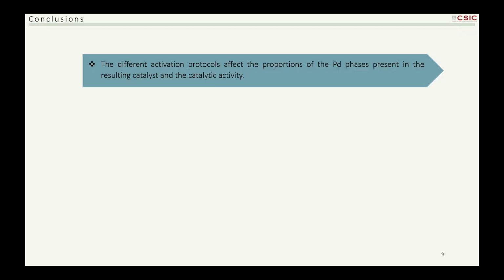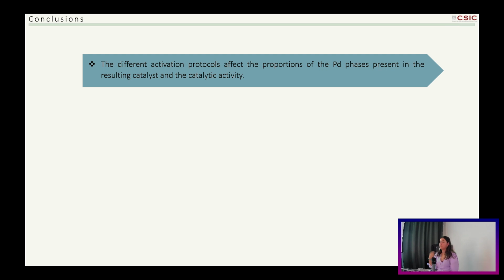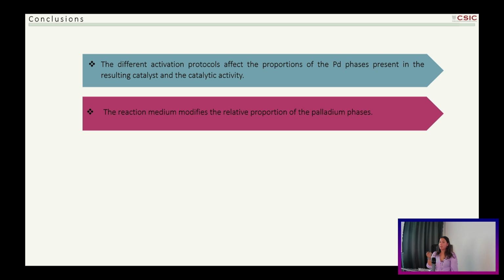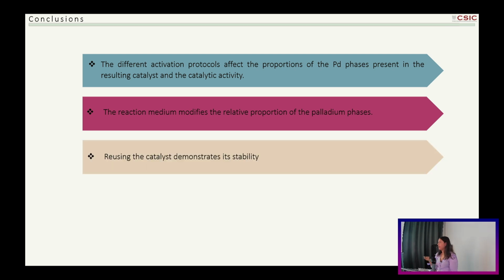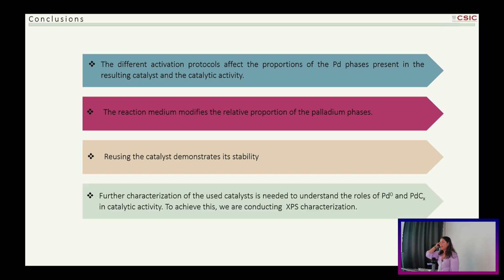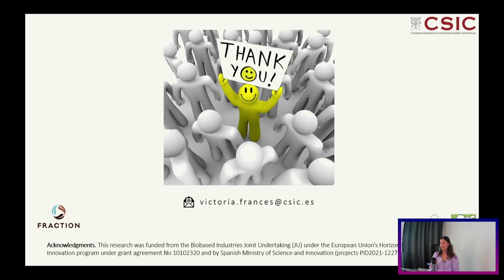So to sum up, we can conclude that the different activation treatments affect the palladium phases that can be present in the catalyst and also the catalytic activity. The reaction modifies these palladium phases, and these catalysts have a good stability. But we need to make more characterization to understand the role of the metallic palladium and palladium carbide phases in the catalytic activity, and for that we are carrying out several characterization techniques such as XPS characterization. So thank you all of us.